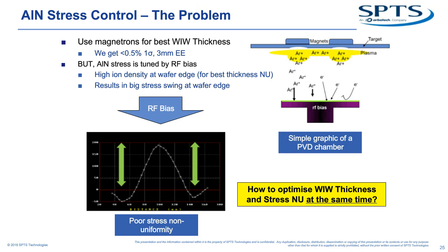The arrival rate of flux at the wafer is non-uniform. Ions arrive at the wafer at different rates. And when you apply bias, which is a primary degree of stress control, you attract flux to some areas more than others. Typically, you attract high-density flux at the edge of the wafer. That bombardment produces a compressive film.